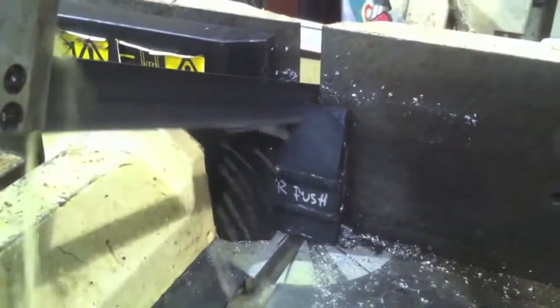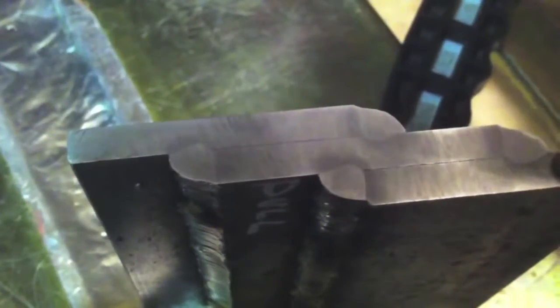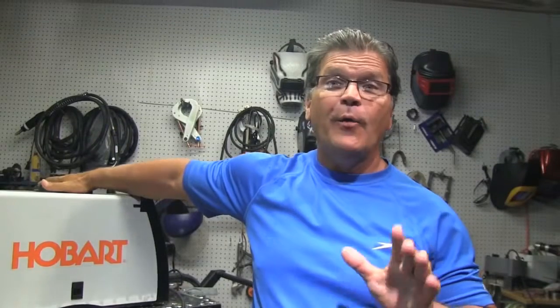And then I cut them using a bandsaw, and then sanded them using around 120 grit flap disc, and then used a little bit of stainless steel discoloration remover, heat tint remover, to swab etch them to reveal the weld nugget. You can also use naval jelly rust remover. It works pretty good for doing that too, and it's safer. But you can see there's just not a huge difference in the penetration or the bead profiles on any of these welds.